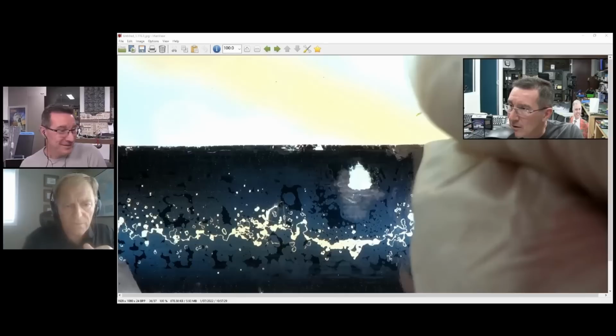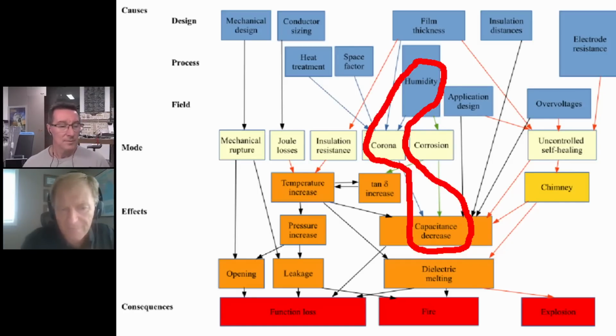Yes, that's right. So I think what you're having is this reaction of the moisture, and what's occurring is that you're getting a moisture effect that's actually causing the electrodes to change. They're getting more resistive. They're getting some migration or movement, oxidations, changing resistances. So those voids are most likely, to some extent, like a micro healing or an impulse degradation. That's how I'd explain that lighter center section. And the darker blotches are most likely a result of end termination corona type effects, something on that order. It's always difficult to comment, maybe 15, 20,000 miles away, and not having dealt with the parts. But I think that's pretty much the scenario. It's definitely a moisture event.